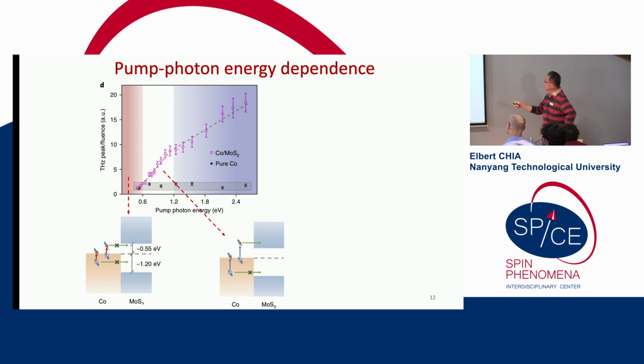And in this regime, the spin-up electrons have enough energy to overcome the electron Schottky barrier, but the spin down, they do not have enough energy to overcome the hole Schottky barrier. And as you increase the energy of the pump photons here, you increase the fraction of the electrons that can go into the semiconductor layer, and so there's a linear increase here.